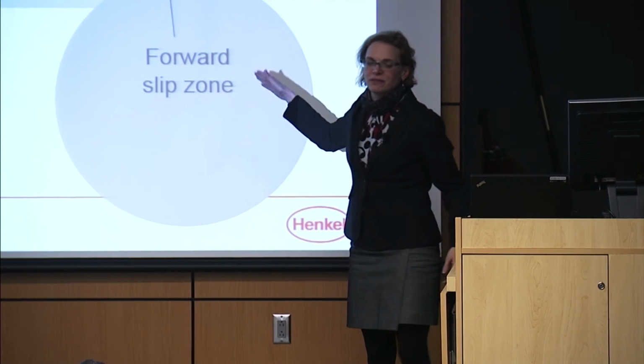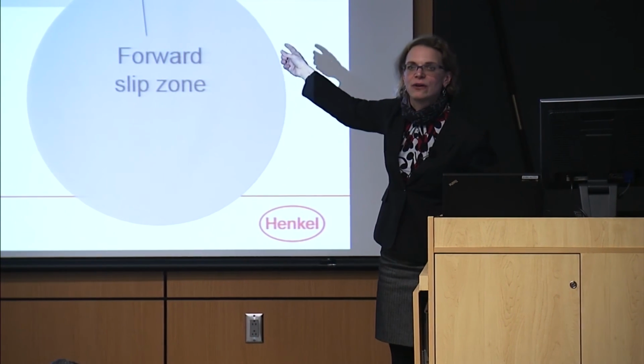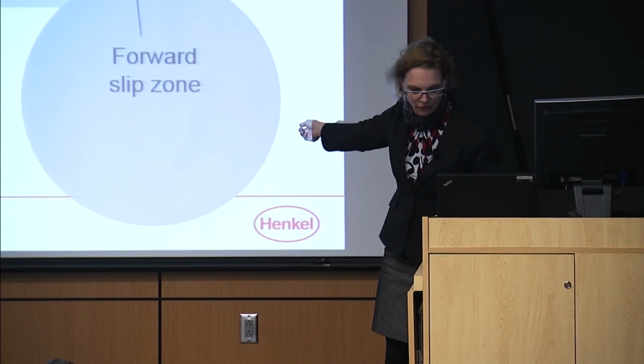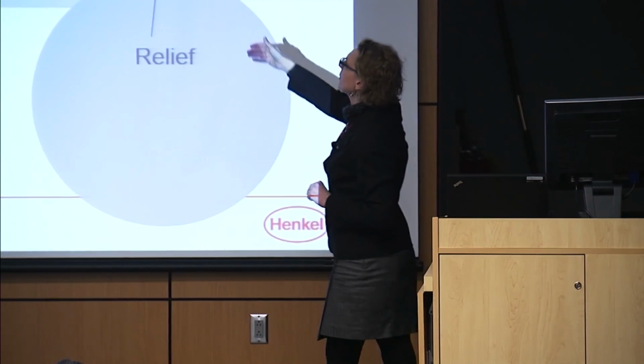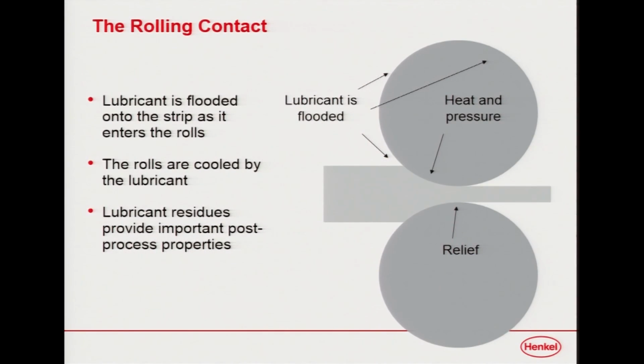This is a bit of a challenge, and it's a couple thousand degrees, just so you don't forget. Lubricant is flooded onto the strip. We're trying to keep the rolls from getting too hot, because if the rolls get too hot, they're going to bend, and then the steel will get out of tolerance, and it'll get bowed and buckled and wavy and messy.